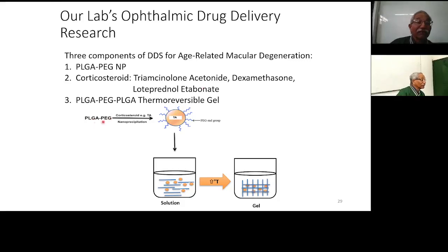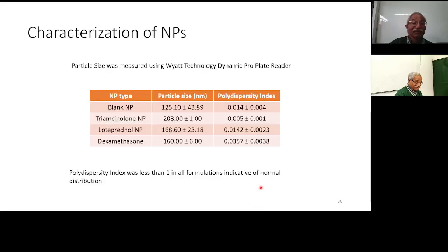So what we did was incorporate the corticosteroid, triamcinolone acetonide, into a PLGA-PEG polymer. Then it creates a solution, and it forms a gel at a certain temperature. At 20-25 degrees, it is a solution. Once it gets to 37 degrees centigrade, it forms a gel and it sticks there and remains there. So that is it, and we had the characterization of nanoparticles.